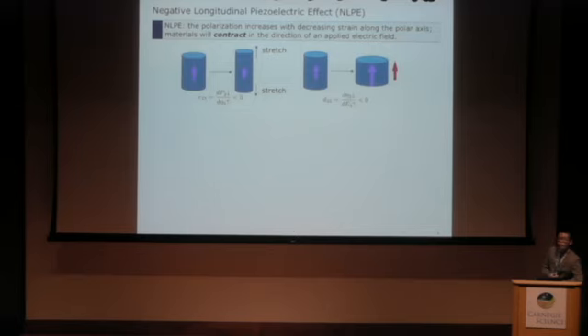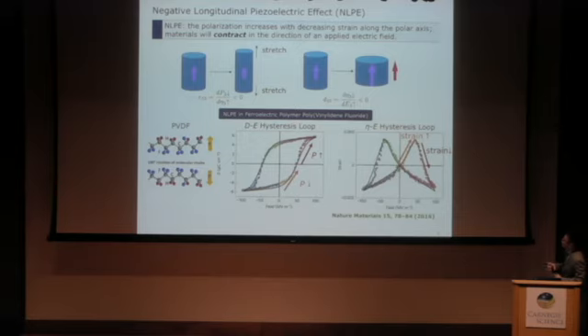You may be wondering whether this has ever been observed experimentally. About 2 years ago, it turns out that this negative piezoelectric response was observed in this well-known ferroelectric polymer. So this is the structure for PVDF. The polarization comes from alignment of molecular dipoles, and we can switch this polymer by applying an electric field. They measured the polarization-electric field hysteresis loop and also the strain-electric field hysteresis loop. As you can see here, when the magnitude of the polarization becomes smaller, the corresponding strain becomes larger. When they increase the polarization, the coupled strain becomes smaller. So this is a clear indicator of a negative piezoelectric effect.